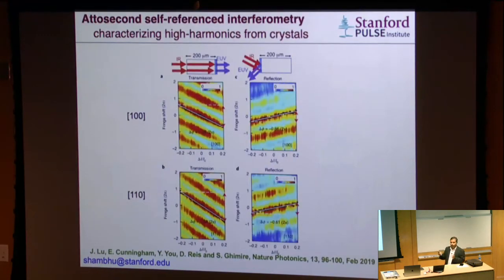First, we did this experiment in the transmission mode. Two spots, harmonics are coming out from the other side of the crystal. The crystal is 200 micrometer thick. And we are tracing the harmonic photon energy as a function of the relative intensity between two spots. Okay? And this is in the reflection mode. You clearly see the difference, right? So in the transmission mode, things are moving up, while in the reflection, they're moving down, right? So that's just one example of how strong this XUV spectroscopy can be, right?